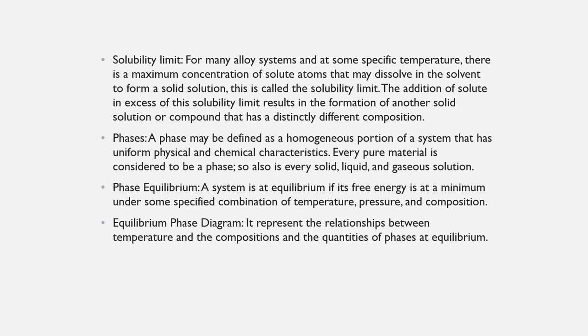A change in temperature, pressure, or composition for a system in equilibrium will result in an increase in free energy and a possible spontaneous change to another state whereby the free energy is lowered. Much of the information about the control of microstructure or phase structure of a particular alloy system is conveniently and concisely displayed in what is called a phase diagram, also often termed an equilibrium or constitutional diagram.